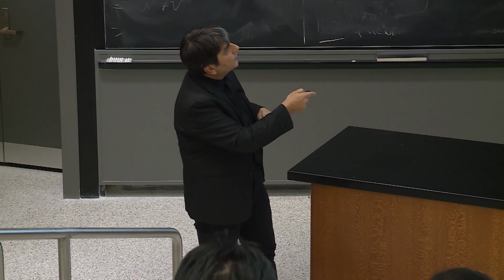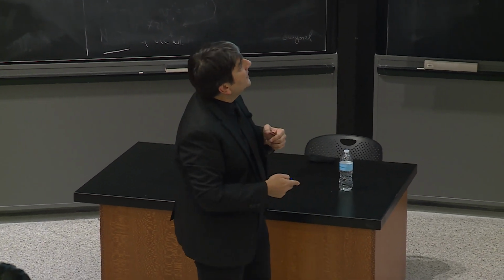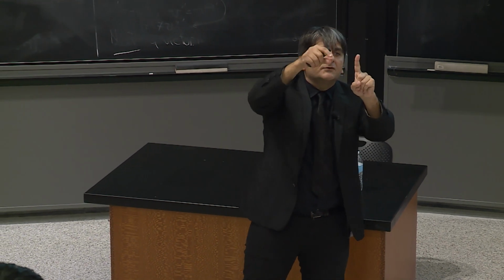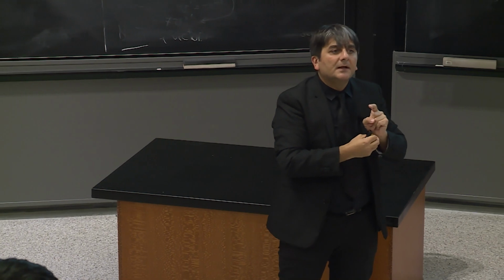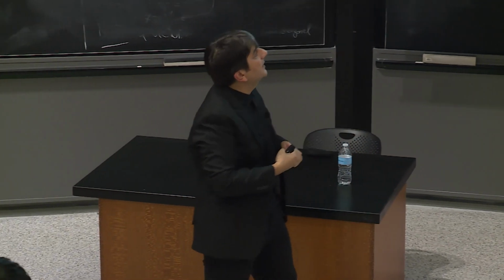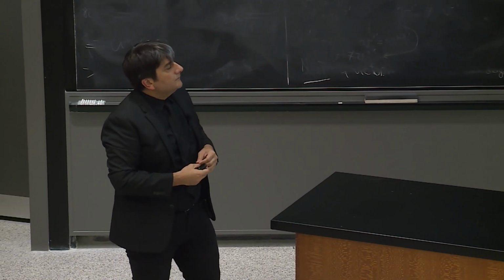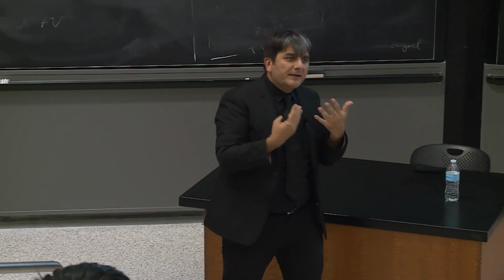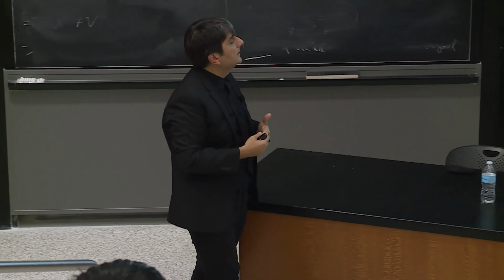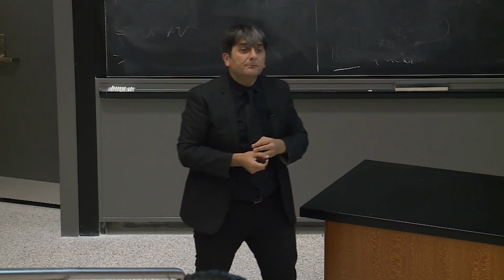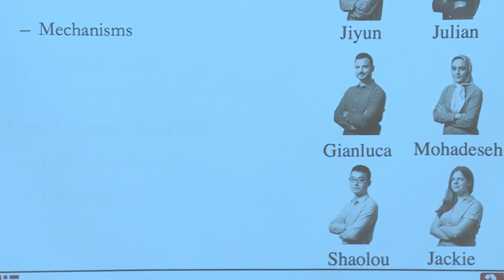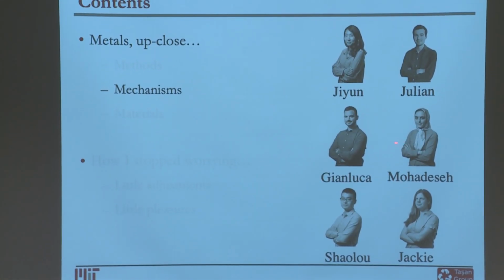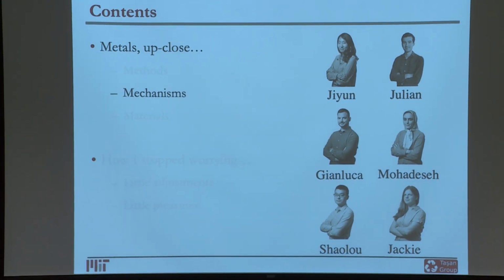Now, this increases your statistics tremendously. Instead of having these data points that sort of don't correlate, you can create much more data points for this problem, which basically teaches you that it's not just about modeling one dislocation and the hydrogen around it. You really have to take into account boundaries in this problem to be able to better understand the hydrogen effects. All right, so these were some examples of the methods that we developed and how these methods help us better understand the mechanisms and move towards design of materials. Now, in terms of mechanisms, of course, we put much more effort as we developed these new techniques. We worked on mechanisms of plasticity, mechanisms of damage and fracture, and mechanisms of phase transformations.